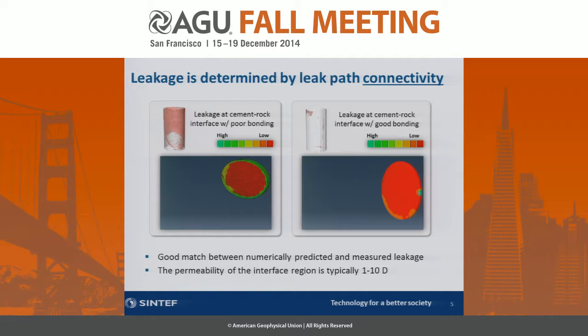What we measured when we compared the simulations with actual measurements of flow through this core was that the interface region had a very high permeability, between 1 and 10 Darcy. So that's a really high permeability, similar to sandstones that we use to inject CO2 into.